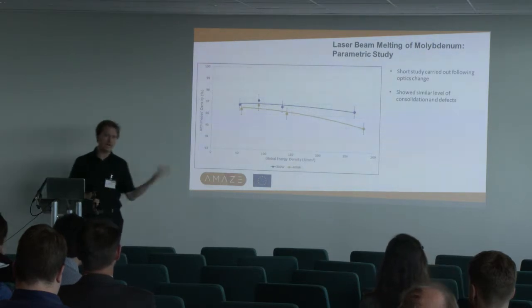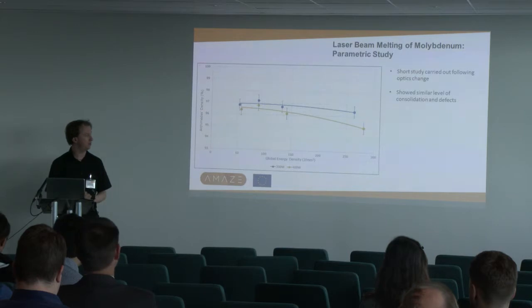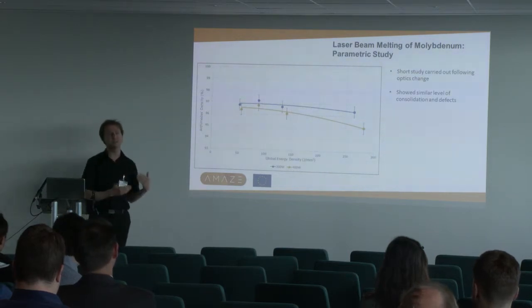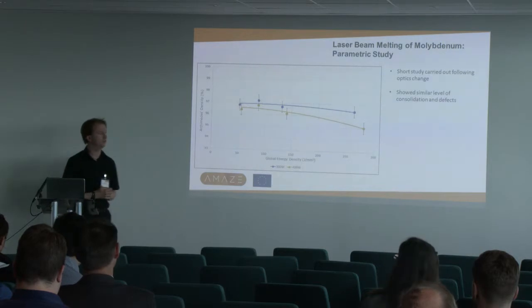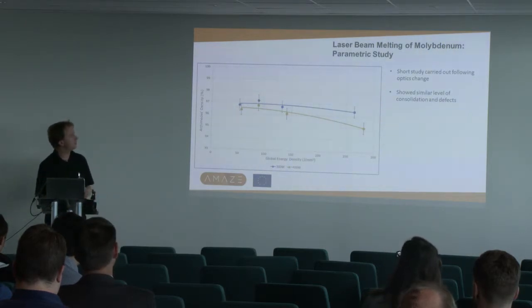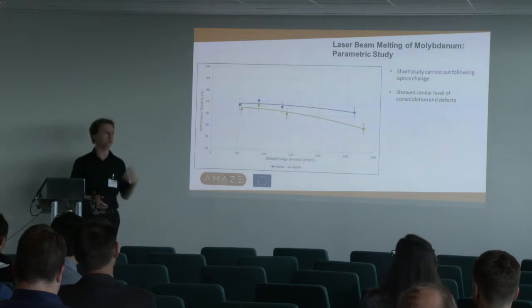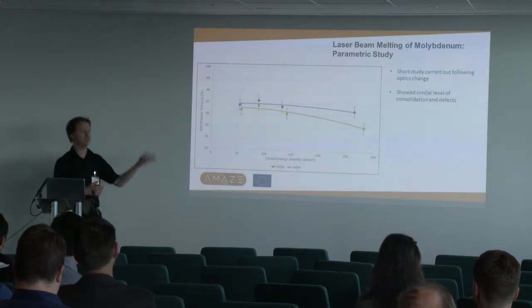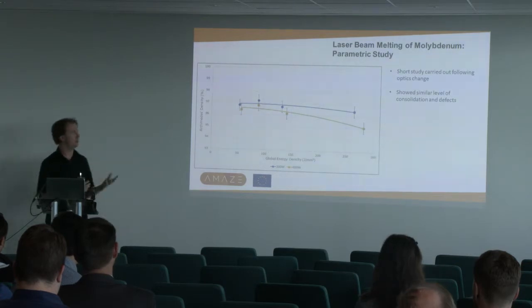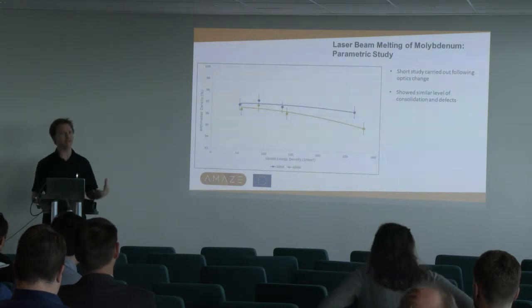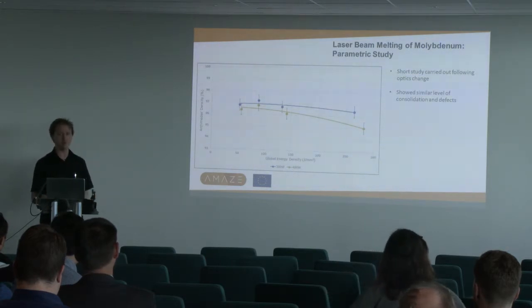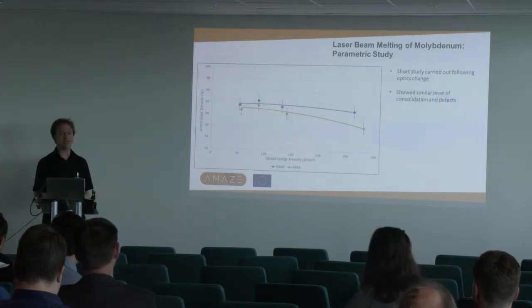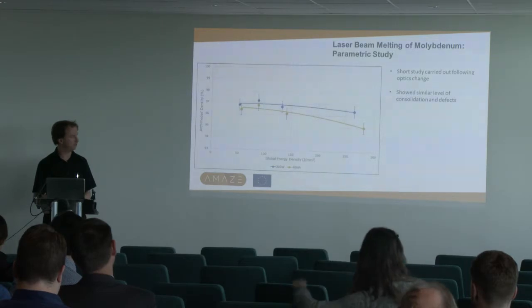So just to confirm our initial Moly results, we repeated some of that parametric study, which shifted the processing window a little bit, because now we've got a slightly more consistent focus at around 60 to 70 microns in size. But we're still seeing the same types of defects. We're still seeing the same types of porosity and the same level of cracking, really. So it hasn't changed anything hugely. But it is maybe a lesson that we learned, that we've got to really monitor the health of our laser and our systems. And we hope that machine manufacturers will take that on board, and in the future we can maybe see more on-board analytical options to keep an eye on those sorts of things.